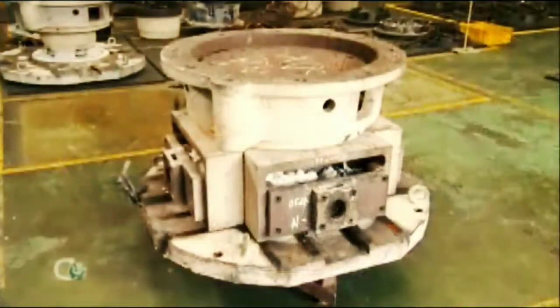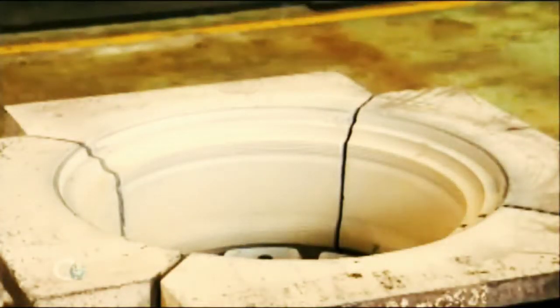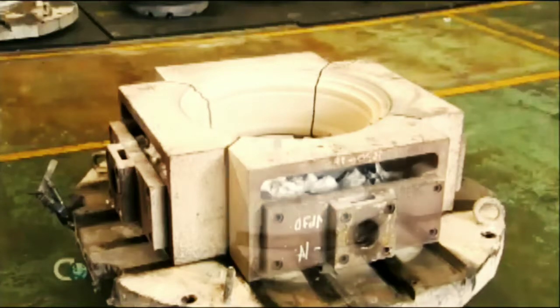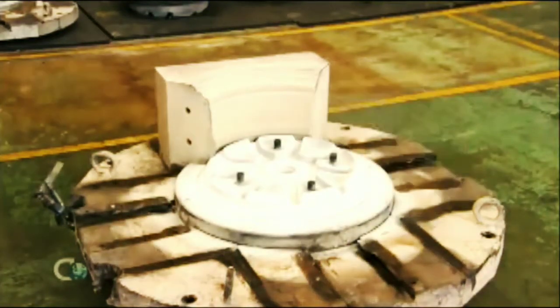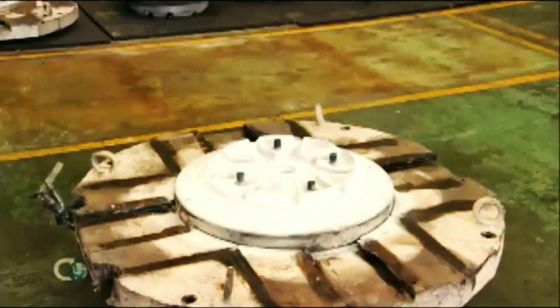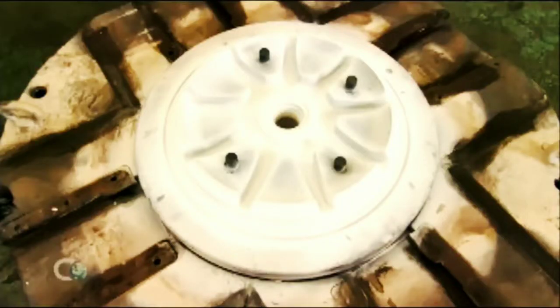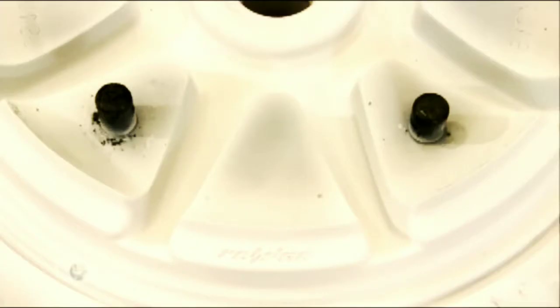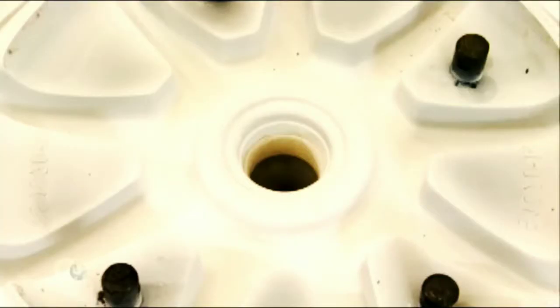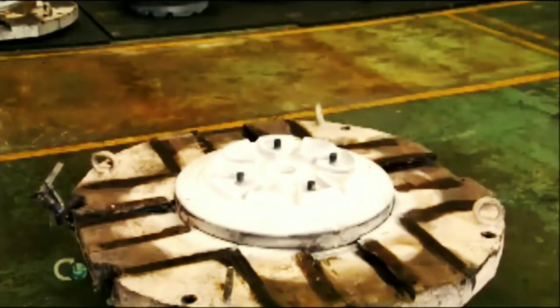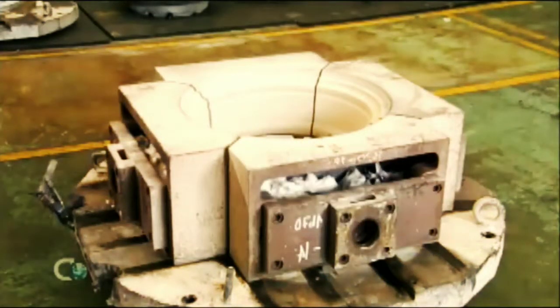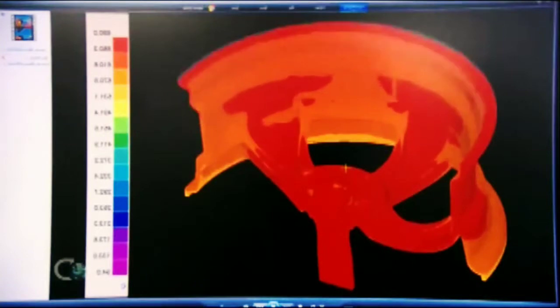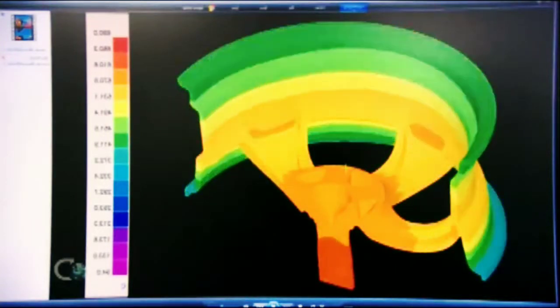The wheel mold is made of high-strength steel. It's actually a set of 3 molds: the upper mold, which forms the inside face of the wheel, the 4-part side mold, which forms the wheel's edge, and the lower mold, which forms the outer face. That's the side with the design, so this is the most intricate mold. It takes 3 to 4 weeks to produce a mold. Computer simulations check the flow and temperature of the liquid aluminum, factors critical for preventing casting defects.